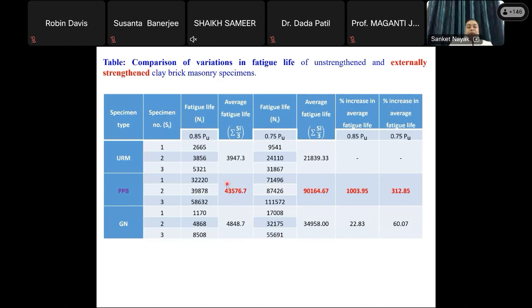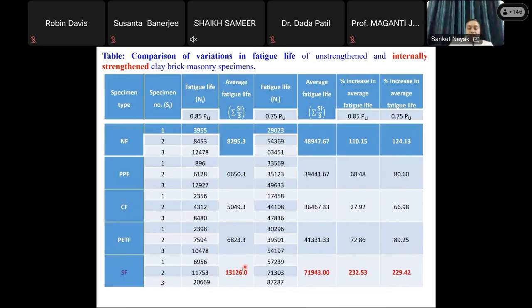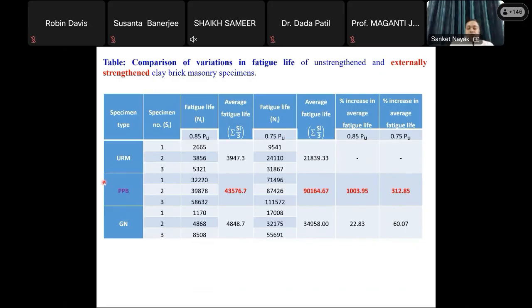In the case of the PP band, it also performed very well in the average fatigue life, and this is the percentage increase in the average fatigue life corresponding to the 0.85 stress level, and this is the percentage increase for the 0.75 stress level, 312. Similarly, the steel fiber also performed very well. And if you look at the fatigue life in the case of PET fiber and PP fiber, they also perform very well in comparison to the unreinforced one.